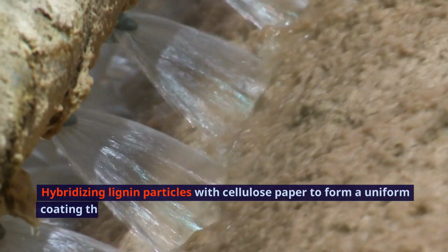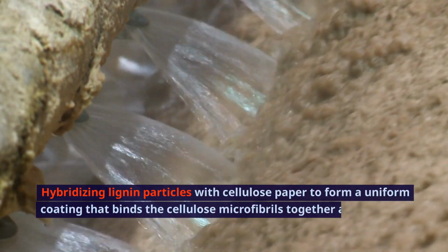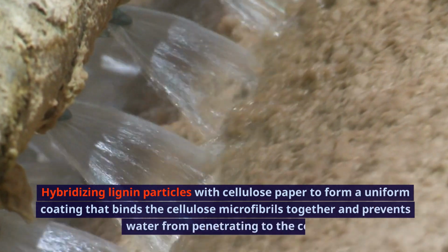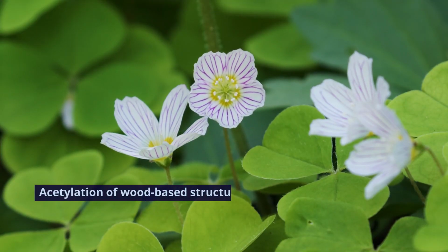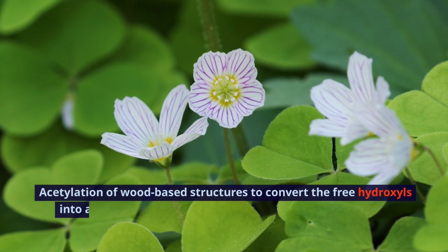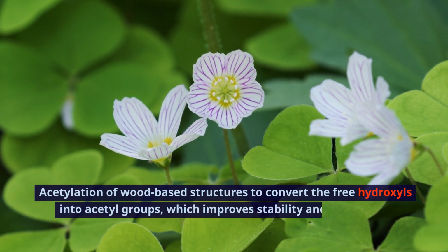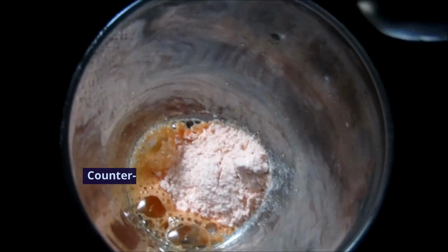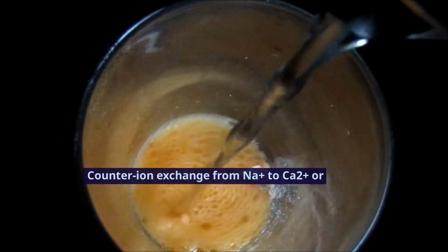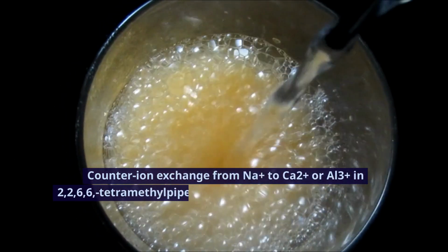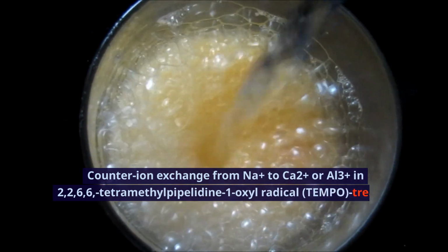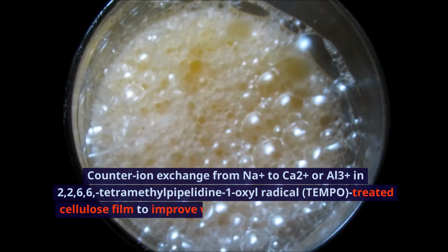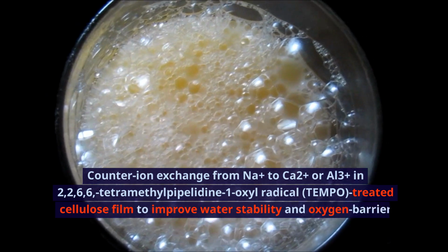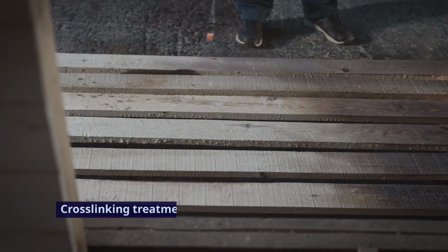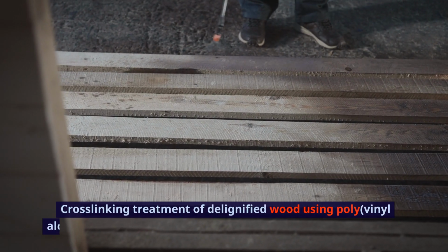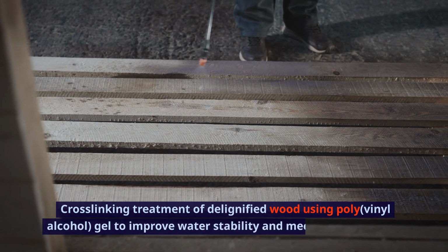uniform coating that binds the cellulose microfibrils together and prevents water from penetrating to the core, acetylation of wood-based structures to convert the free hydroxyls into acetyl groups, which improves stability and anti-fouling properties, counter-ion exchange from Na+ to Ca2+ or Al3+, and 2,2,6,6-tetramethylpiperidine 1-oxyl radical, TEMPO, treated cellulose film to improve water stability and oxygen barrier properties. Cross-linking treatment of delignified wood using polyvinyl alcohol gel to improve water stability and mechanical strength.